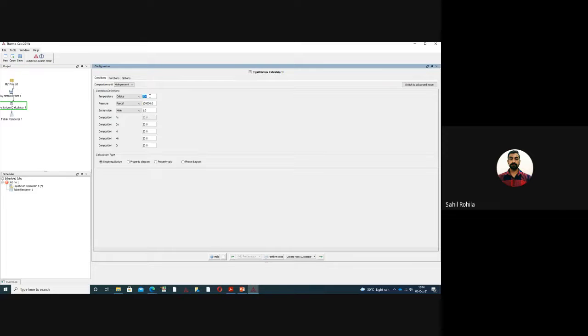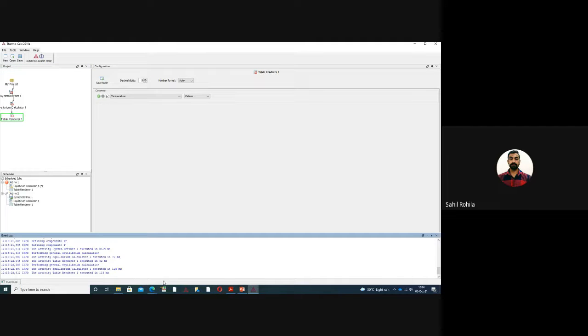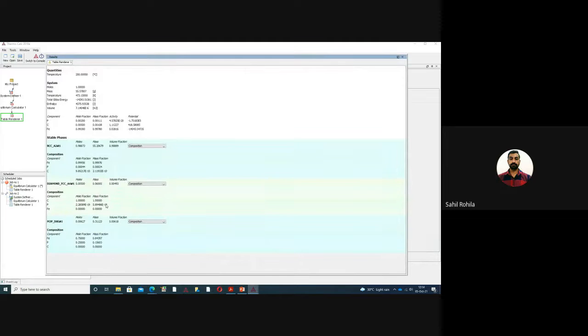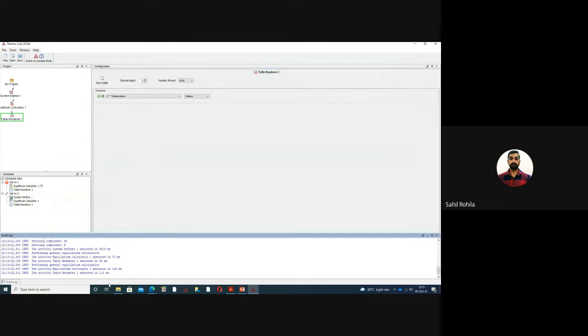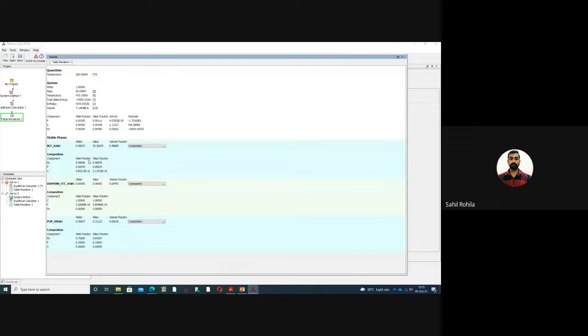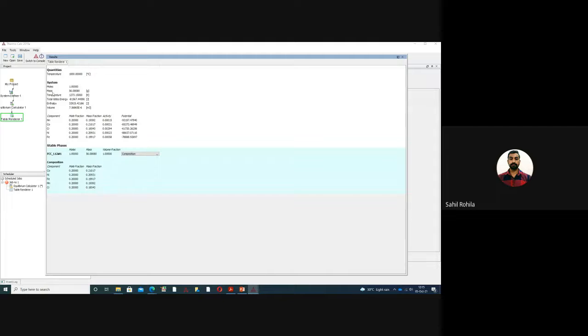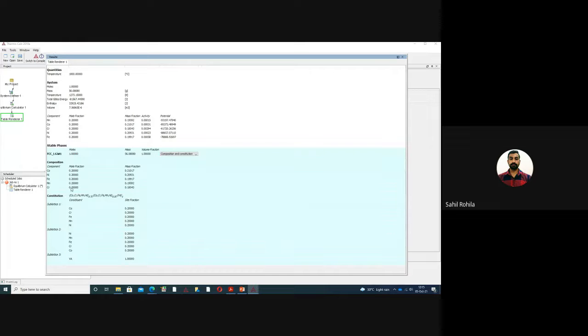Conditions, I'll select nearly 1000 degrees centigrade and table render. I'll get to know the results. Right, it is running right now. It is still running. Yeah, so it has run. It is giving me the stable phase of this particular high entropy alloy, which is FCC only, and the constitution and composition will show equal composition of all the elements. There will be no segregation of the phases.